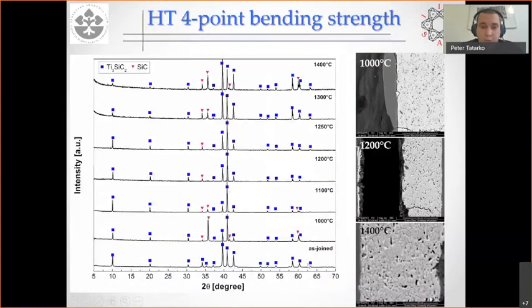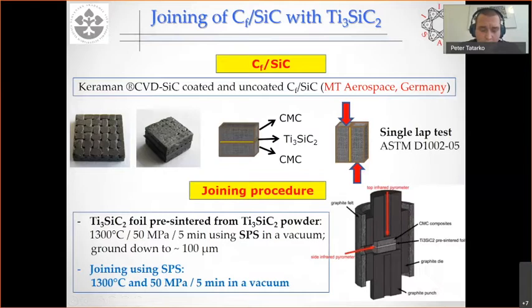A very important fact was that because the tests were done in vacuum, we didn't find any decomposition of the MAX phase, because we didn't see any titanium carbide or silicides or any other impurities. You see here at 1400, the pattern looked exactly the same as as-joined sample, which was very good. If you look at these images, you can only see the typical damage at a high temperature, like microcavitation, microcracking. So those were the typical reasons for failing the sample, not the composition of the filler. So all of these made us believe that this material is promising to be used for carbon fiber reinforced silicon carbide. So now coming to the composite, which was our main priority.